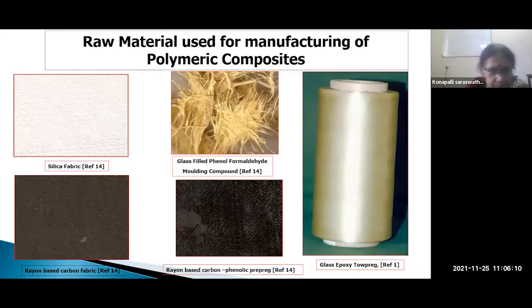This is the high silica fabric. Then it is not very clear. It is a rayon-based carbon fabric. Once I say rayon-based carbon fabric, it means rayon yarns are woven into fabric, and that fabric is carbonized, which is used for high temperature applications. PAN carbon fabric is used for high strength applications, and rayon carbon is used for high temperature applications. It does not have much strength, but high thermal properties are better.